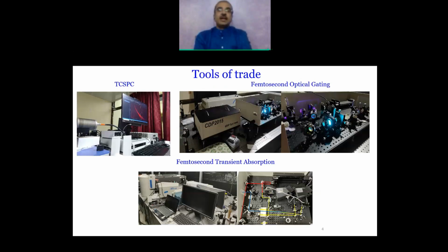Now, I told you that we need very good stopwatches in order to go down to such small time scales. And what you see now on the screen are the stopwatches that we use in our lab and in our institute. If you want to measure times in nanoseconds, 10 to the power minus 9 second, then we use this technique called time correlated single photon counting. The instrument that you see on the left top has been our workhorse for a long time. What you see is a new one, which has been installed only last year.